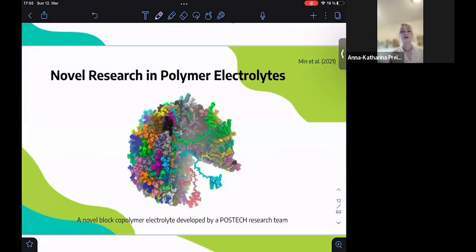Next, we have polymer electrolytes. Even though they have lower ionic conductivity, they are often flexible and can be made into different thin films or shapes. But this low ionic conductivity more recently has been addressed by a POSTECH research team, which created a block copolymer of polystyrene sulfonate and polymethylbutylene. This had the ability to self-assemble into a specific structure to optimize properties such as ionic conductivity and stability. So I would say let's not write off the polymer electrolytes just yet.